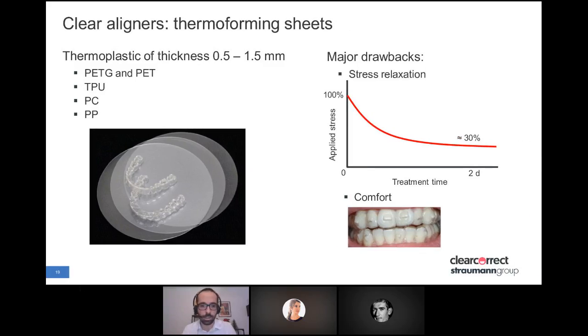Here are some examples of state-of-the-art materials, although not top of the class. The mostly used materials are polyethylene terephthalate, normal and glycol modified, especially glycol modified, thermoplastic polyurethane, polycarbonate, and polypropylene. These are thermoplastic sheets of thickness 0.5 to 1.5 millimeters, and are used for thermoforming, as I showed before. As I already mentioned, stress relaxation is a big problem, and for these materials, it is a problem.